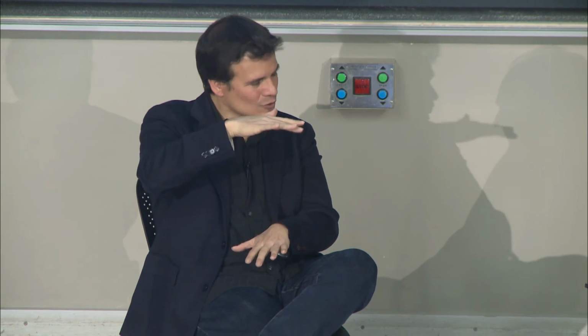You demonstrated, or at least our colleagues at Columbia demonstrated, that by applying pressure you were able to increase the correlation between the layers. I imagine, especially in those stacked structures, that would be an effect that would be very strongly pronounced. That's right, indeed. If you apply pressure to this sandwich of 5 or 6 layers, you will change the magic angle condition too, and you will be able to make angles which are not magic.